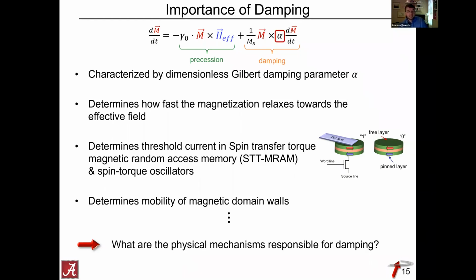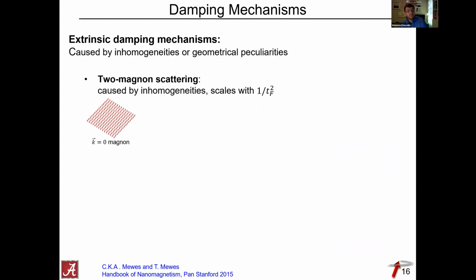And to illustrate that a little bit, I want to give you a quick overview of what the mechanisms are that can contribute to the damping in different films. I'll start off with extrinsic damping mechanisms, which are caused either by inhomogeneities or other geometrical peculiarities of your sample. The first one to mention there is called two-magnon scattering, which is caused by inhomogeneities,